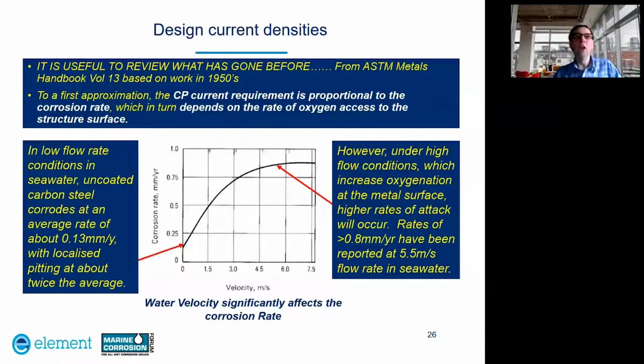Now I just want to look at some factors that we need to consider on the cathodic protection system. Firstly, it's useful to review what has gone before. This is from ASTM Metals Handbook Volume 13, based on work in the 1950s. To a first approximation, the CP current requirement is proportional to the corrosion rate, which in turn depends on the rate of oxygen access to the surface structure. In low flow conditions in seawater, uncoated carbon steel corrodes at an average rate of about 0.13 millimeters a year, with localized pitting about twice the average, as shown at this point on the graph.